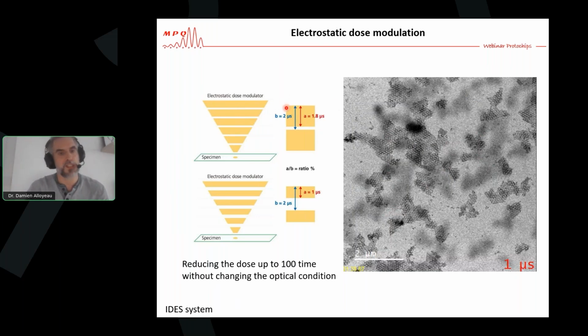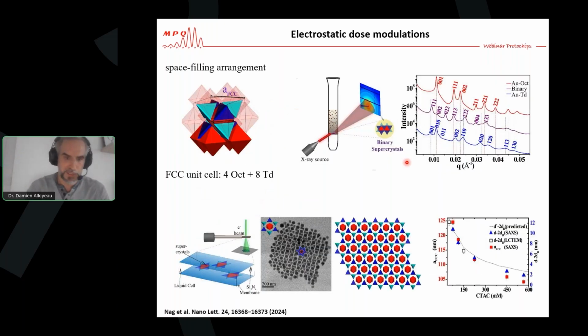So it's an electrostatic shutter that works with a frequency up to 50 nanoseconds, and that allows you to block the beam at each pixel for a given amount of time. So by reducing the dwell time at each pixel to compensate the increase in dose rate due to magnification, we are now able to observe those supercrystals without destroying them. We are able to reach a magnification high enough to observe their structure.